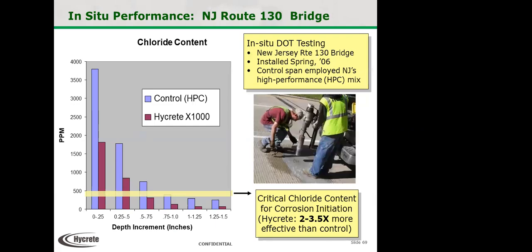This is a study done by New Jersey DOT. This is actually called DOT's Route 130. They did a test comparing Hycrete versus their high-performing mix. This is what they use when they get a lot of snow in the northern parts of New Jersey. So as you can see, the Hycrete basically had less chlorides in every single depth increment as compared to the high performance concrete. That is literally them throwing the kitchen sink of everything they could think of into this concrete to make it extra performing. And the Hycrete still did better than all of it, in regular concrete with nothing else added.